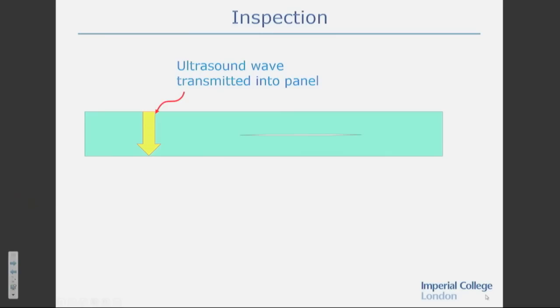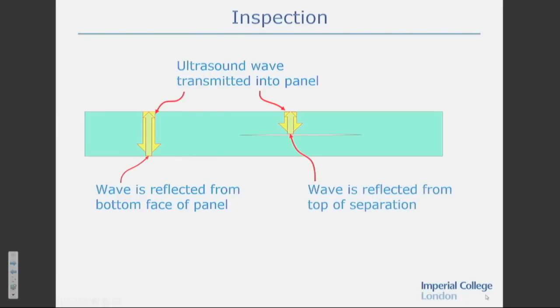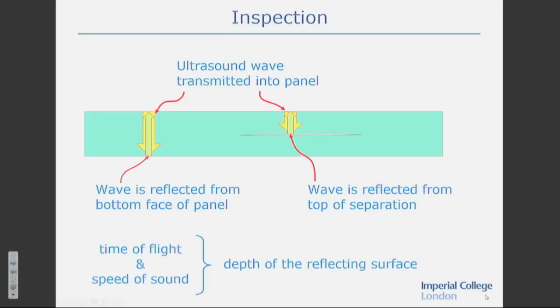The commonest inspection technique, most effective, is ultrasound. And the technique goes like this. We inject an ultrasound wave into the panel from one surface. It hits the bottom, and it reflects back up. And if we did it over a separation here, what you find is the bulk of the signal is also reflected back up from that separation. So imagine what we do then.